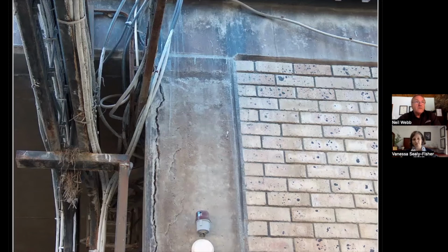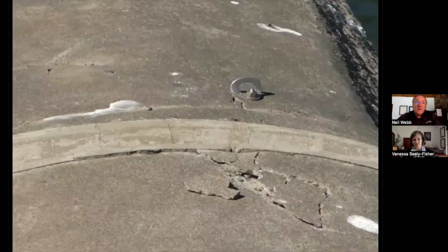material. This particular example that you can see in the photograph actually was acid mine water that penetrated into the structure from the mine structure. It was a conveyor structure being washed down with mine water all the time. And another situation that happens is carbonation, where carbon dioxide from the atmosphere reacts with the concrete very slowly over a long period of time, but it can also destroy the passivity of the underlying steel. And when the steel is no longer passive, it corrodes.